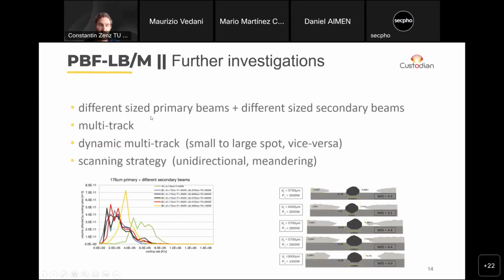Now what we did is we tested different primary beams, different secondary beams in terms of size and also power. We also looked at multi-track simulations, so not only a single track, because in reality we want to process very complex geometries. And then we also tried switching between small and large beam shapes from one track to the other, for example, increasing the size of the beam during successive tracks, or reducing it. And we also looked at different scanning strategies, so meandering approaches, for example, or uni or bidirectional scanning approaches.